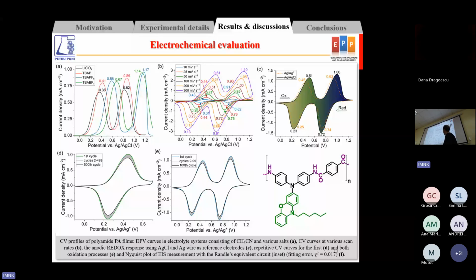Then we tested the stability of the polymers up to 500 cycles for the first oxidation state, as well as up to 100 cycles for both oxidation states.